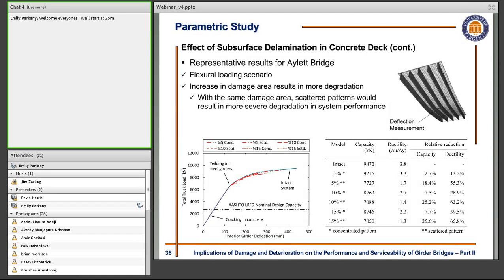But as you take a look at this figure, in all of these red dashed lines, we have reduced ductility in the system, and this reduced ductility is mainly attributed to the fact that because of delamination, we lost composite action between the layers of the concrete. And this loss of composite action caused the compressive stresses to increase significantly at the top surface of the concrete and cause premature crushing, specifically at the margins of the delaminated areas. Other than that, if you take a look at the results that we tabulated in this table, within each area of the damage, for the scatter pattern, we have more severe degradation on the capacity of the system. So this is pretty much the parametric study that we performed on these representative structures, and that was the last part of this ongoing investigation.